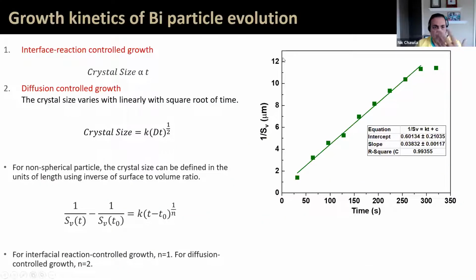So one of the things that Amaya has been trying to understand now is the kinetics of diffusion. So he's trying to separate between interface reaction controlled growth versus bulk diffusion controlled growth. And of course, if you have bulk diffusion, the crystal size should go as time to the 1/2. And so with the tomography data, we have quantitative 3-dimensional data as a function of time. And you can see here, sorry, trying to move this one. You can see here that we get a slope of about 0.038 or so. And actually this is 1/SV, but essentially what we're trying to point out here is n equal to 1 for interfacial reaction control growth, and diffusion control growth would be n equal to 2. So we're really close to this interfacial reaction controlled growth mechanism.